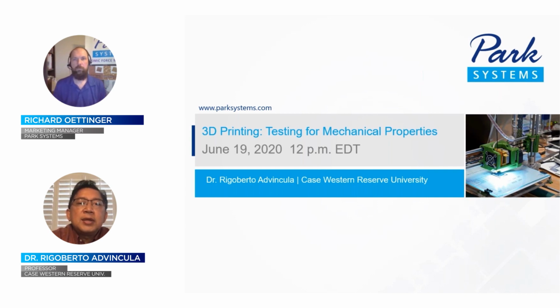So there's a lot of ASTM, ISO standards that have been reported with those, and they are qualified or used to predict failure. On the other hand, with 3D printing materials, the standards are still evolving. But yet you can use the same standards used for monolithic materials, except that you have to pay attention to the orientation as well as the composition of the material. So yes, in the next webinar, you will learn more about material properties and testing, especially with thermomechanical properties.